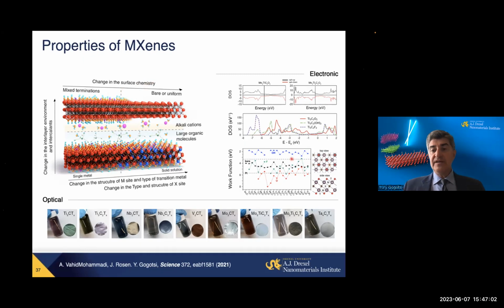But surface termination also affects properties. You get hydroxyl, and the work function is close to 2 eV, very important for tuning for devices. You get oxygen, it goes close to 6. Fluorine is about the middle, 4. So we can tune the work function for solar cells, for OLEDs, basically matching it to the semiconductor we use. They can come in a variety of complementing colors. Titanium carbide MXene is red in solution, green in reflection, just like gold nanoparticles. But there is no gold there. It's just titanium and carbon, two of the most abundant elements.